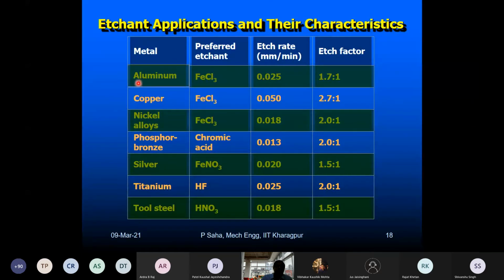Say for example, the metal could be aluminium. For aluminium we use ferric chloride. Okay, for copper we use ferric chloride. Nickel alloys again ferric chloride. Phosphor bronze, chromic acid. Silver, ferric nitrate. Okay, then titanium will only react with hydrofluoric acid. It is so inert to the acid. Okay, tool steel, nitric acid. So correspondingly you see the etch factor is different.